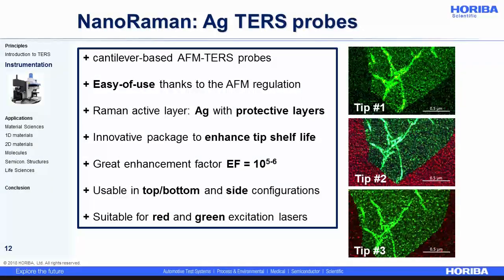So we use some silver TERS probe today, mainly for doing our TERS measurement. Those probes are cantilever-based AFM TERS probes, really easy to use, like every conventional AFM cantilever. This Raman active layer is silver, as I said, with a final protective layer in order to increase the lifetime of this tip. Without it, the lifetime is only a few hours. Silver, as you know, suffers very quickly from sulfidation and oxidation. But this protective layer drastically increases the lifetime of the tips up to several weeks. We found a nice enhancement factor with them, up to 10 to the power of 5 or 6, and those tips are suitable for top, bottom, and side configuration, both with red and green laser Raman excitation source.